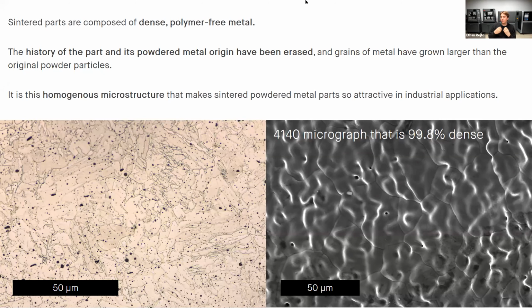It also has this homogeneous microstructure that allows the parts to be isotropic, where they have equal strength in all directions. 3D printed parts have this notorious stigma for being weaker in Z than they are in X and Y, but this is not true of sintered parts. Because we're sintering our parts, we're bringing the whole geometry up to its sintering temperature, allowing it to fuse in all directions, allowing it to be isotropically strong. It's this homogeneous microstructure and these isotropic part properties that make these parts very, very attractive for these industrial applications.